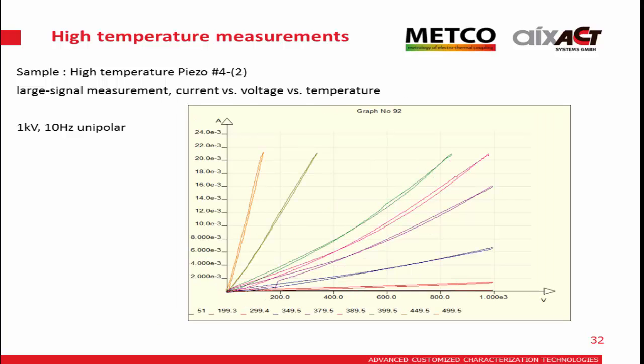And at the same time we monitor the current so we can get the resistivity. So in the range of 5 to 10 kilo ohms of the sample we are not able to. It's limited to 20 milliamps, depends on the amplifier of course. So you can see that the voltage goes down because the sample is really highly resistive, but you still can measure the displacement. But of course it's a different condition in that case.